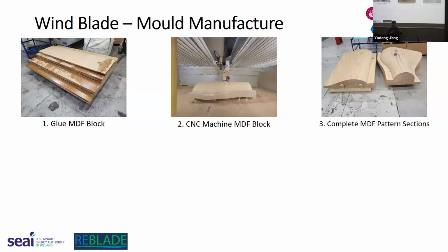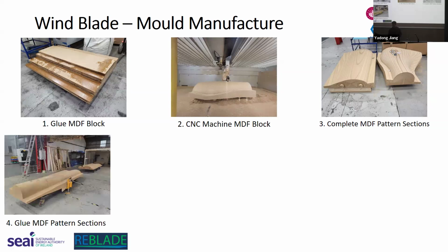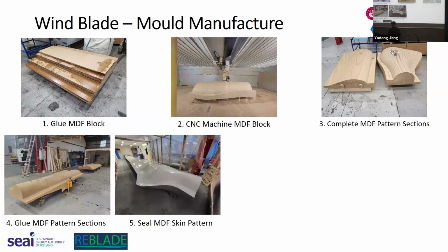So we made 6 sections, and we glued them all together. You can see in this image here, there's 2 nipples, and then there's 2 holes on the other side, so we can locate them and make sure that all sections are in line. The next step then is obviously gluing each of the sections together, and then we seal the surface, to try and get a really smooth, clean surface finish on the MDF, and also so that when we are making the mold, it's not going to be absorbed by the MDF.